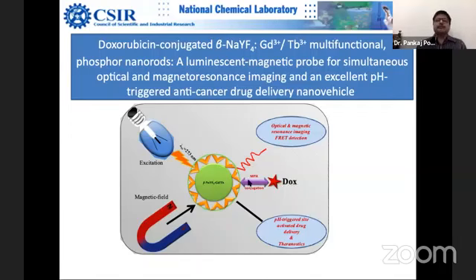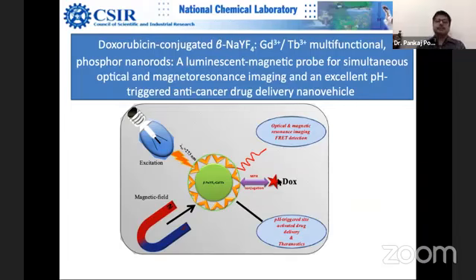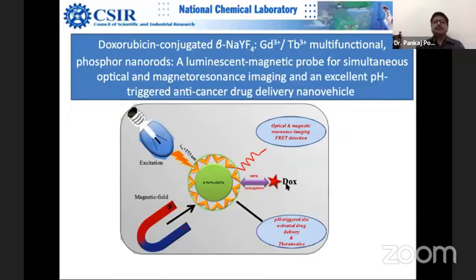The advantage was that when this imaging system along with the drug was injected into tissues or a single cell system, looking at the pH environment — in a low pH environment — this bond got cleaved and the dox was released. So we probed this using multiple systems. In fact, dox also has its own strong optical signal, so we could image it using a variety of probes.